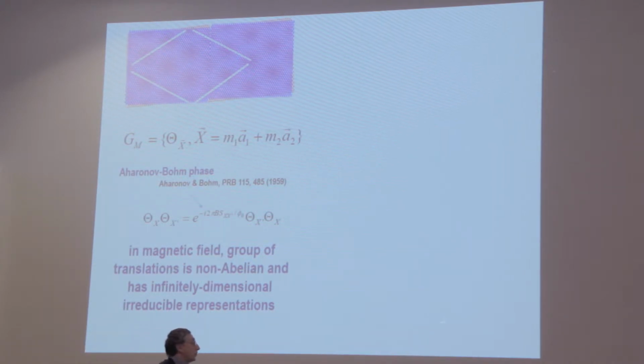And in terms of the group structure of the symmetry of states in a crystal in a magnetic field, it leads to the translations acting on the states of electrons no longer commuting like they did at 0 magnetic field. They pick up an additional phase factor upon the commutation, which is determined by the Aharonov-Bohm effect. And what it does, it produces a non-abelian group, which typically has infinitely dimensional irreducible representations. And this is basically reflected by the infinite degeneracy of the Landau level in the two-dimensional electron gas.